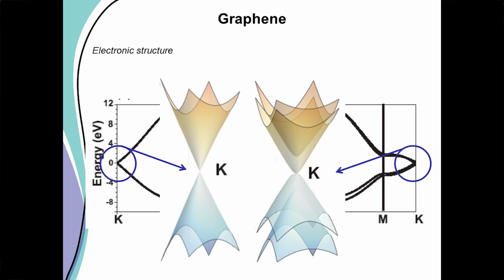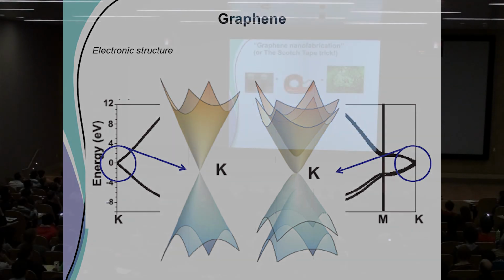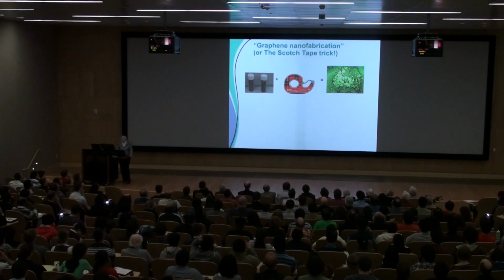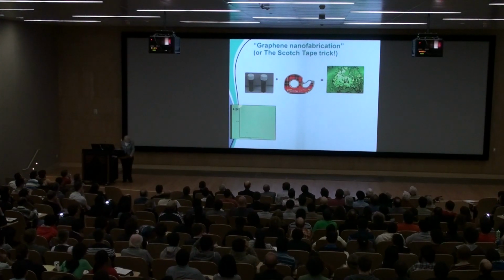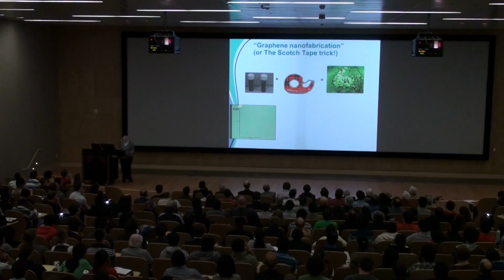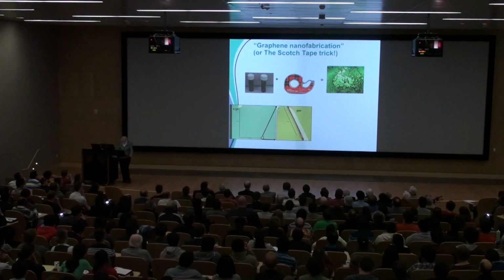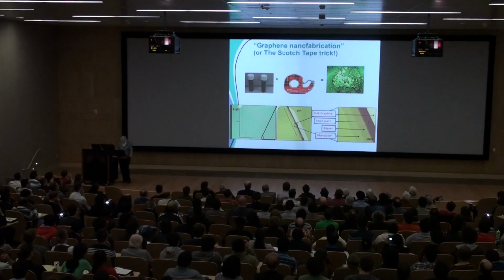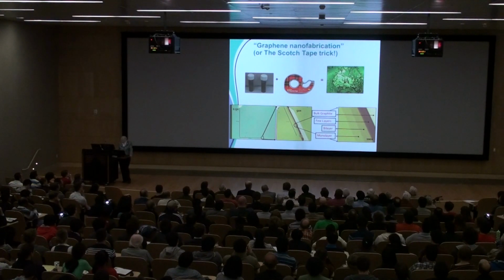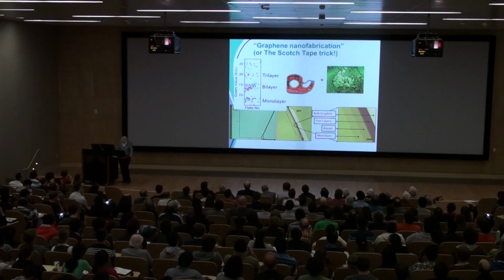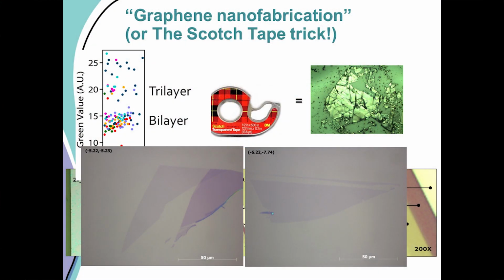And this shows you the Fermi surface. You could see how that is. So this is the Scotch tape trick of Manchester, what they taught us. And so these are the pieces of graphene. They look pretty terrible. But if you look at them on short range under the microscope, they look much more beautiful, as I'm going to show you. So now that's more and more magnification, and this is now 200 magnification, and you can begin to see single layer different from bilayer, as you can see on your right. And so this is the frequency in the samples of this particular paper, and here's some more pictures of the monolayer, bilayer, and beyond that.